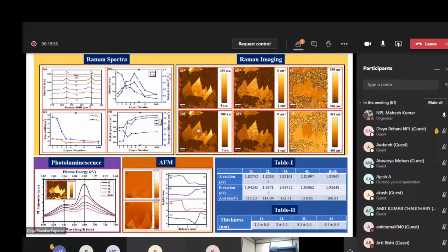see the topography of these different MoS2 nanosheets. Here you see the thicknesses of the different layers. So the interesting thing is that this is the first time where we have got the number of layers at one location, and the two tools, the peak frequency difference and the valence band splitting, are the two tools which are majorly used for identifying the number of layers.